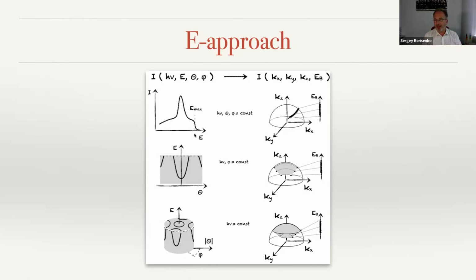But as soon as we are talking about angle-resolved photoemission spectroscopy, this curve starts to have limited physical meaning, in the sense that it doesn't correspond exactly only to energy. Because, as I said, kinetic energy changes all components of the momentum. It does correspond also to the momentum distribution. So the term energy distribution curve is actually not correct in this sense. It should be energy-momentum distribution curve, just because when we start the spectrum at a certain kinetic energy and then go to lower kinetic energies, we arrive at a completely different momentum in the reciprocal space.